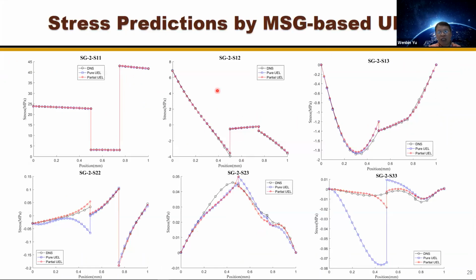We find out that pure UEL does a good job, but not for the very small stresses. These are the transverse stresses. For the in-plane stresses, both approaches work okay. But for the transverse stresses, although they're small, they could be very important, for example, for delamination, right? And when we use the partial UEL, it's significantly improved.